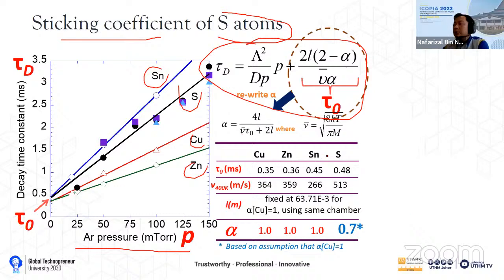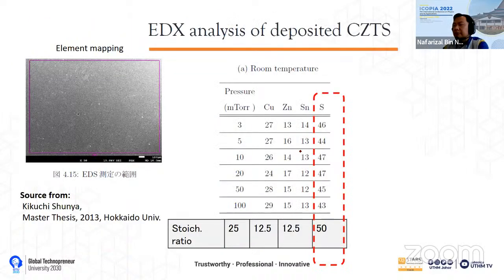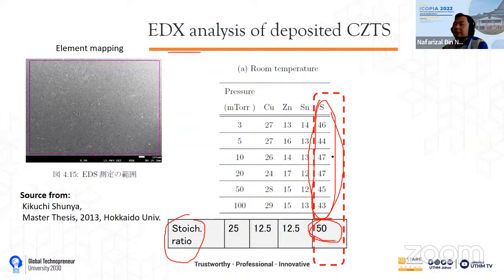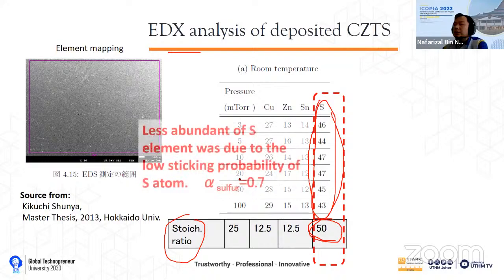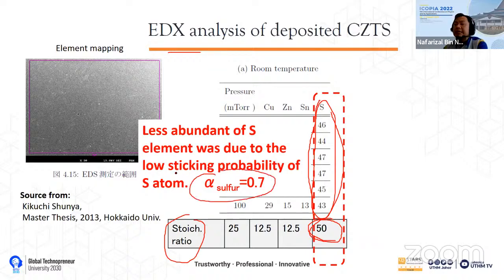So the result that we found here is that the sticking coefficient for sulfur is lower, which is 0.7. That's why the sulfur content in the thin film that we have is not high. Comparing with the EDX analysis of the sulfur content, we can see the sulfur content is less than stoichiometric. The stoichiometric should be 50%, but when we do the EDX analysis on the CZTS thin film that we developed, it is less than 50%. So this result is consistent with the sticking coefficient analysis showing that sulfur has a 0.7 sticking probability. That is the reason why the sulfur is not up to the stoichiometric 50%.